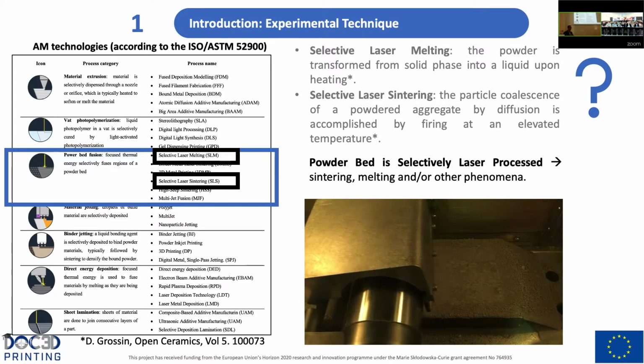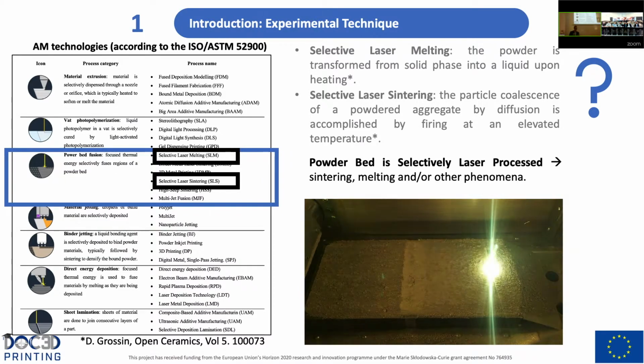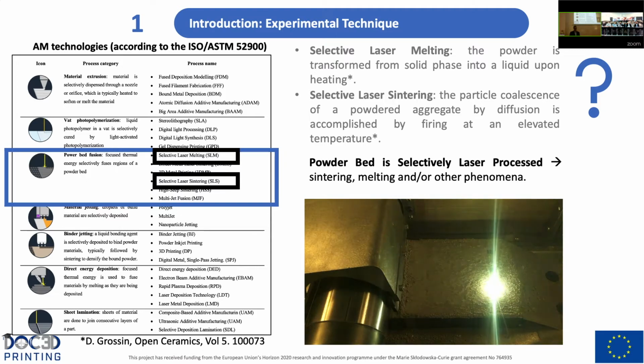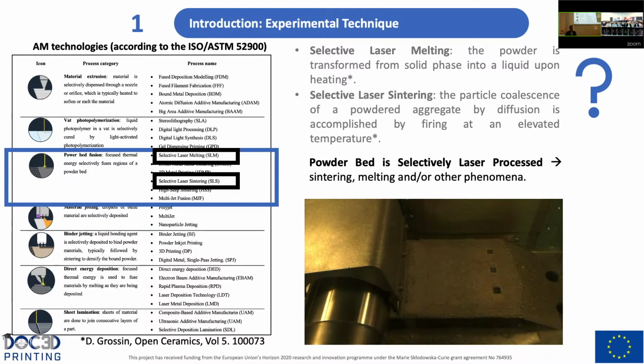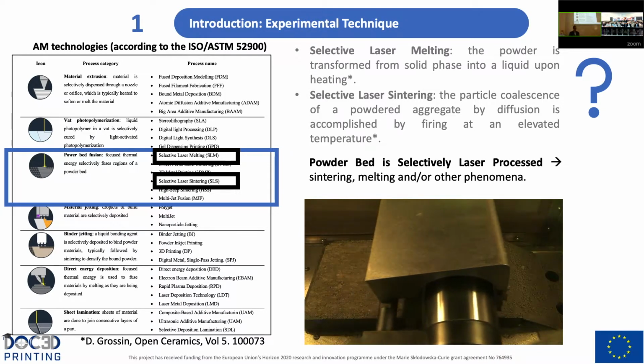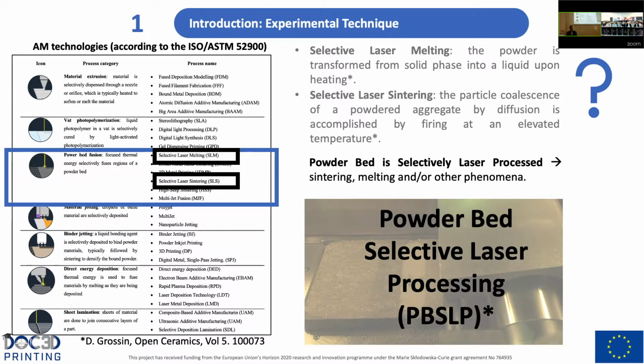But if we are mixing our powder with, for example, silicon powder, which has a melting point, we shouldn't use selective laser sintering. So to avoid misusing these two terms, we decided to create a new term to call this technique, which is powder bed selective laser processing.